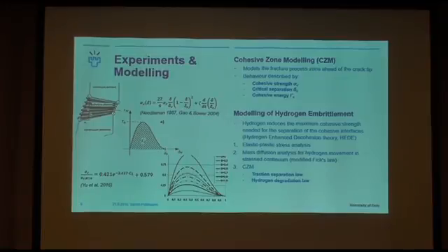So first we do elastic stress analysis to get the hydrostatic stress state. Then mass diffusion analysis to calculate the local hydrogen contents in these stressed areas. And on the third step, the cohesive step with the cohesive elements, hydrogen-informed cohesive elements. So we use the traction separation law of Needleman with the added viscosity term of Gao and Bower to handle the convergence problems we can run into when these cohesive elements separate. And for the hydrogen degradation law, which describes how much the cohesive strength lowers as a function of hydrogen, we use this quite recent law of Yu et al.